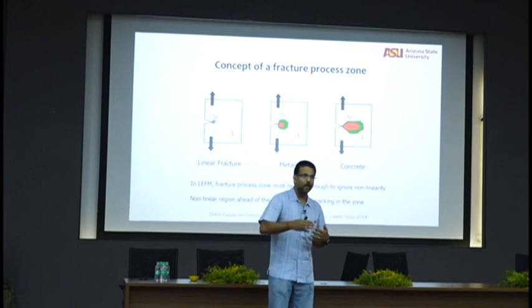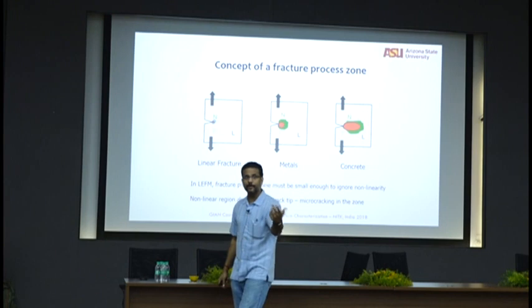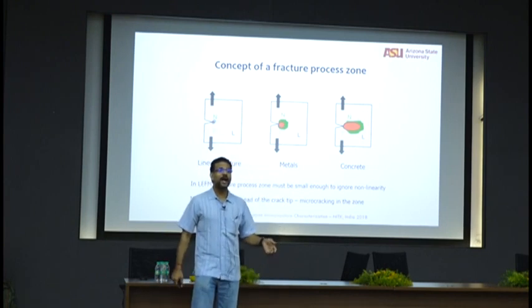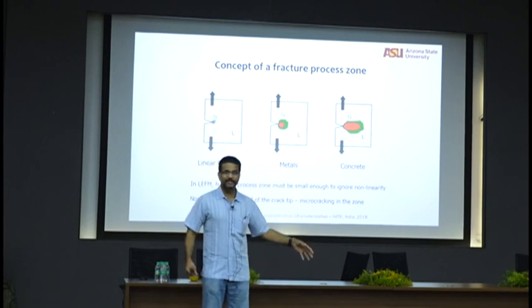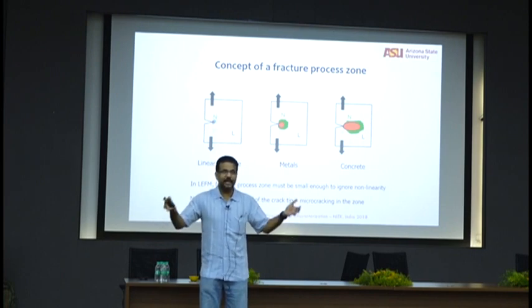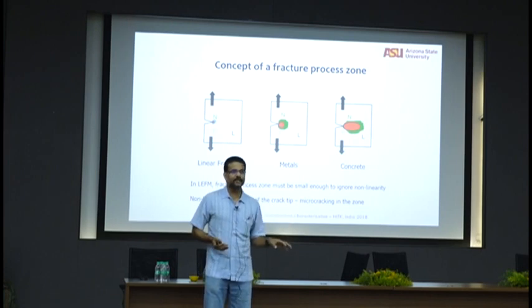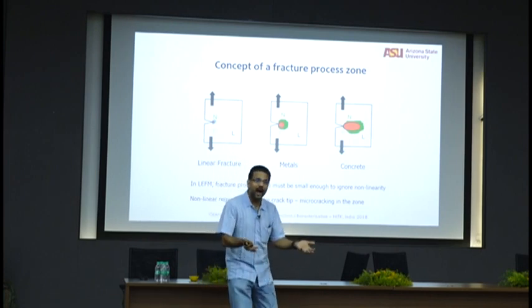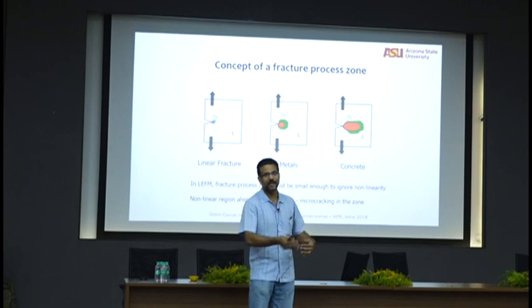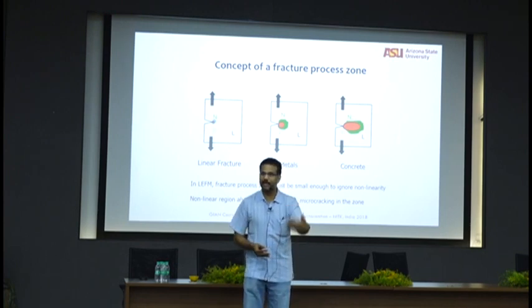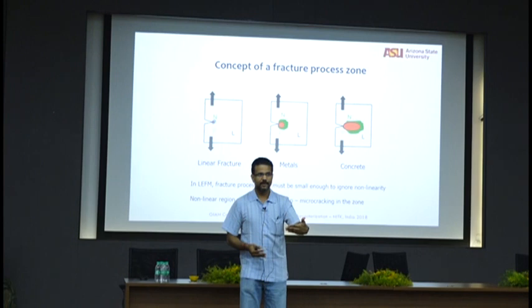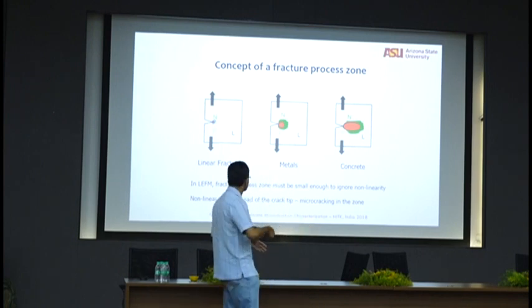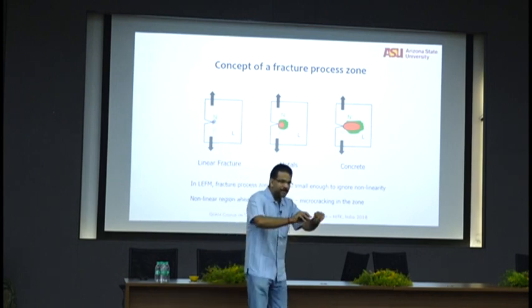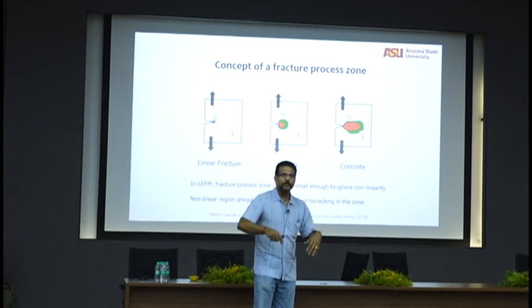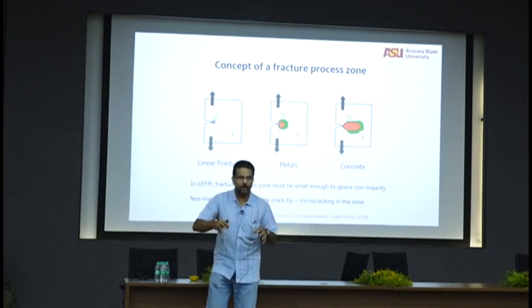I may have to go more, but that is a good thing for you as a concrete engineer because you have made that crack lose its energy. Energy is a finite quantity. It is coming from the internal stored energy. Now you made it dissipate the internal stored energy. Now it has to work hard to create that energy to crack further, which means you have artificially blunted a crack. You see that? So a crack needs energy to go through, and when it goes through, it distributes its energy around. So when it distributes energy around, what happens?